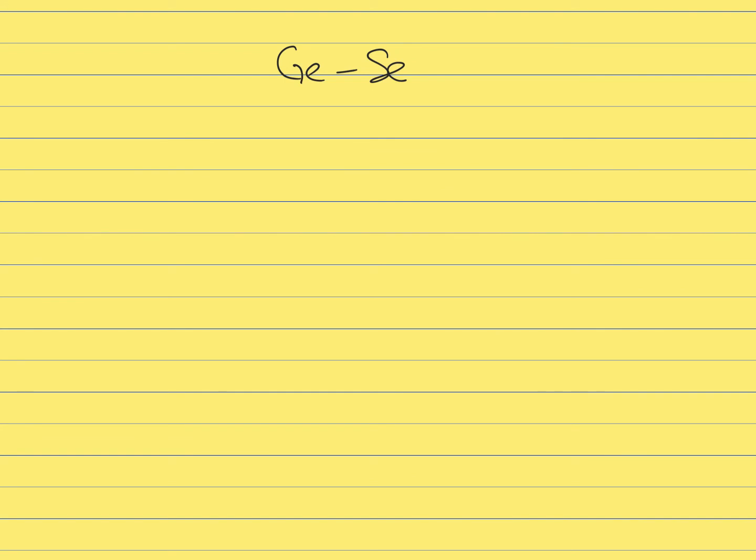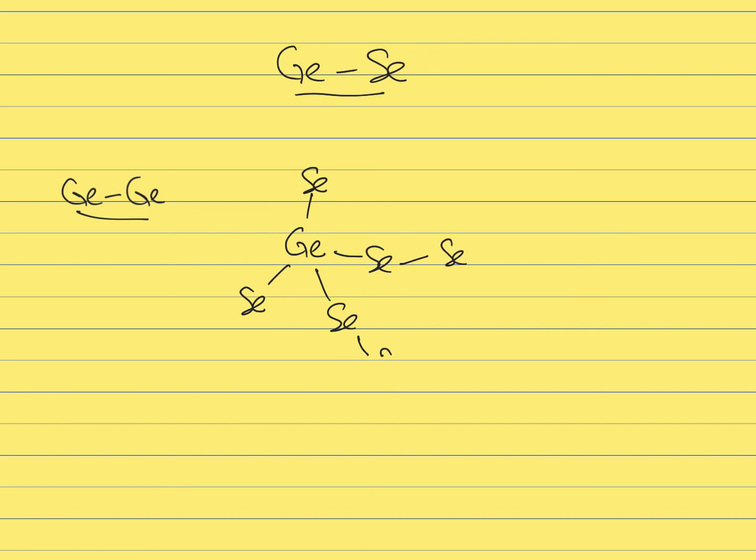So one typical example of chalcogenide glasses would be a germanium selenium glass, where you have a given fraction of germanium that is combined with some selenium. And so in this case, the typical structure of this glass would be that you have some germanium. Those germanium are 4-fold coordinated. Those germanium typically will be connected to some selenium. It's more rare to find some germanium-germanium bonds, but those bonds are still possible. They are not completely forbidden. On the other hand, typically you will find some selenium-selenium bonds. And so the typical structure will be like this.